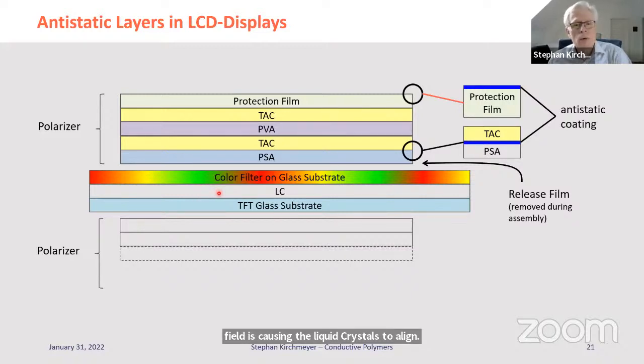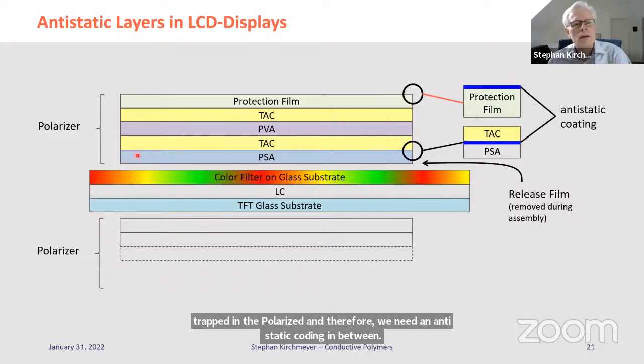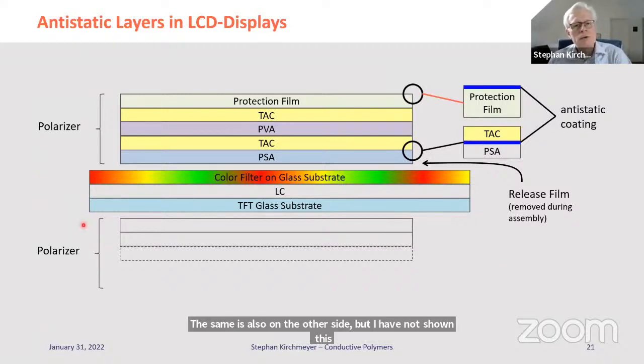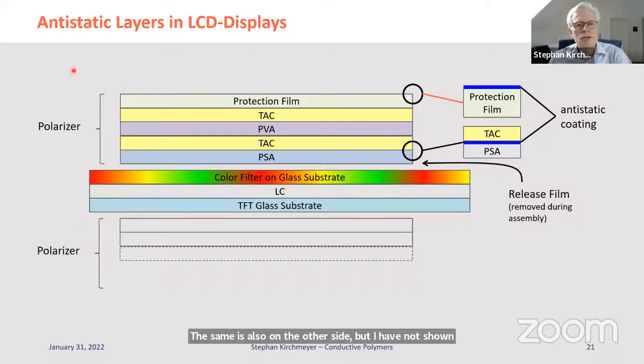We do not want that. We want that the liquid crystals align to the TFT voltage and not to a voltage that is trapped in the polarizer. Therefore, we need an anti-static coating in between before the polarizer is glued on top of the liquid crystalline display. The same is also on the other side, but I've not shown this fully here because it's basically the same polarizer, just in a reversed order of films.